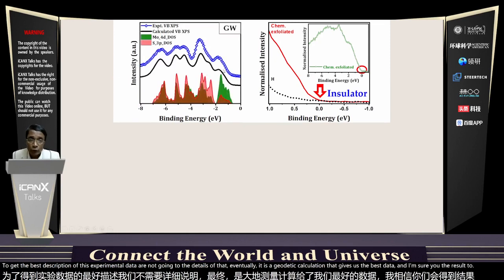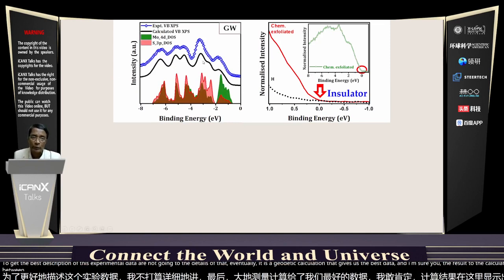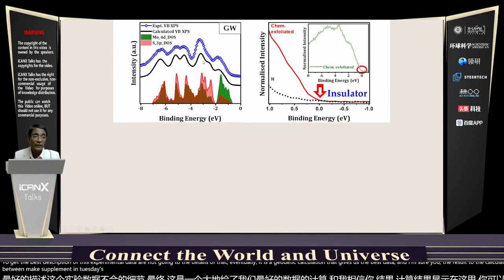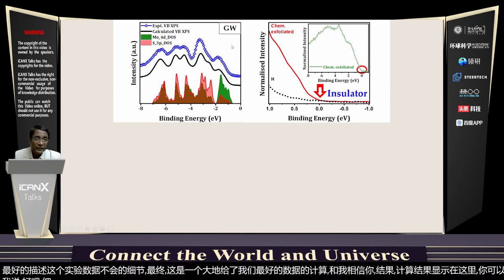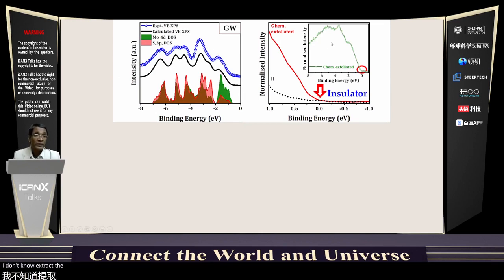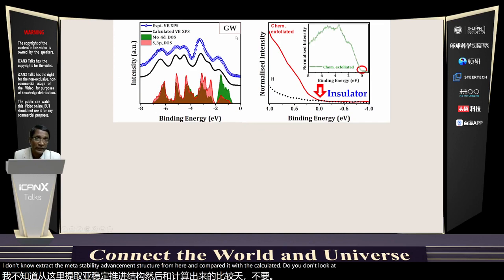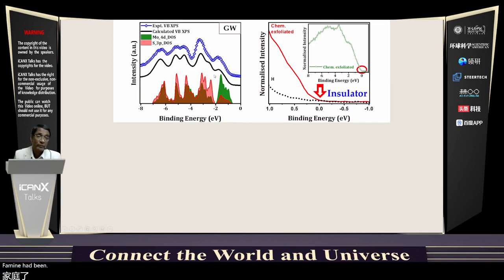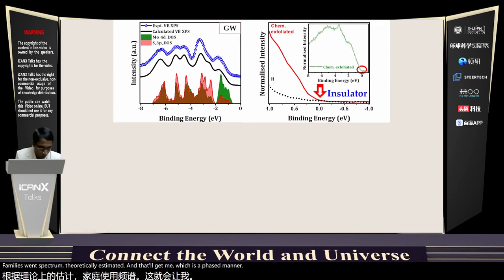So the calculated result is shown over here. And you can see that the agreement between the experiment and theory is satisfactory enough for me to say, okay, fine. I'll now extract the metastable state valence band structure from here and compare it with the GW calculated valence band spectrum, theoretically estimated, and that will tell me which is the phase that I have got.